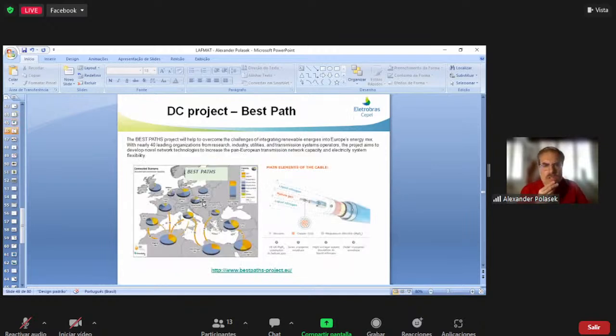However, in the case of DC cables, you don't have this AC loss, but in order to use DC cables, you need much longer cables, much longer lengths, and as you can see, the best path is the main project to make. It aims to make. There will probably be a DC network in Europe, made by using conventional cables, and superconducting cables can also be used in this grid.